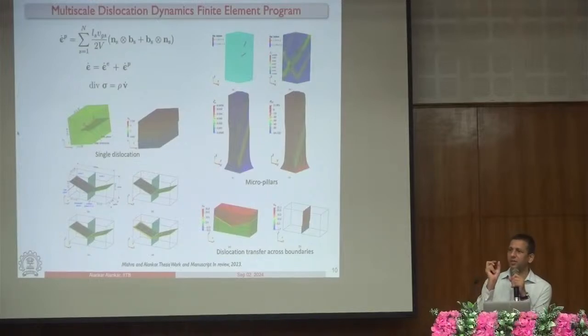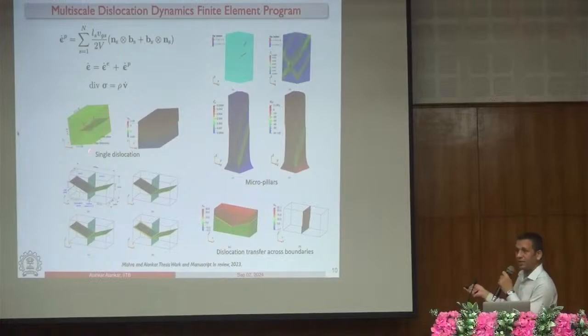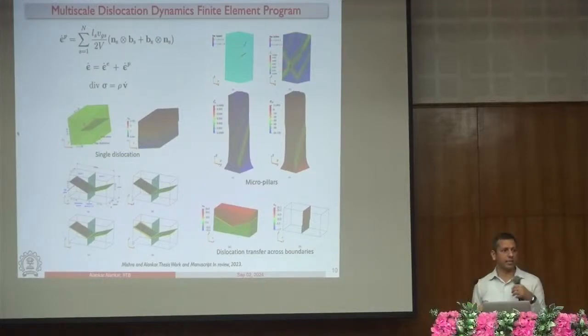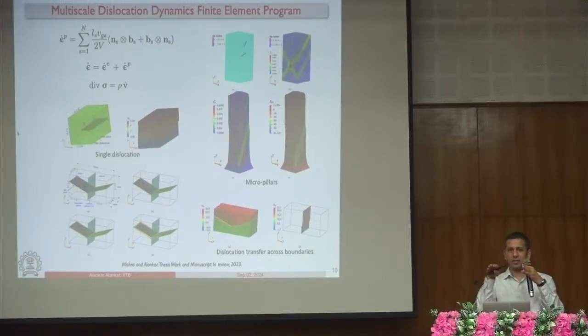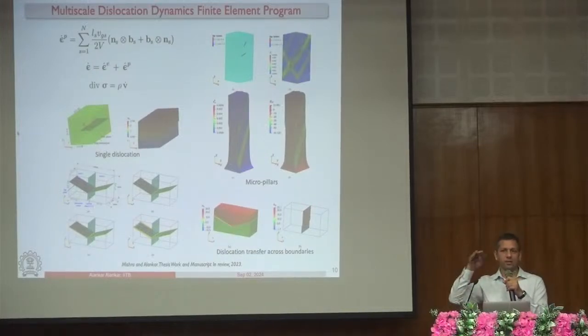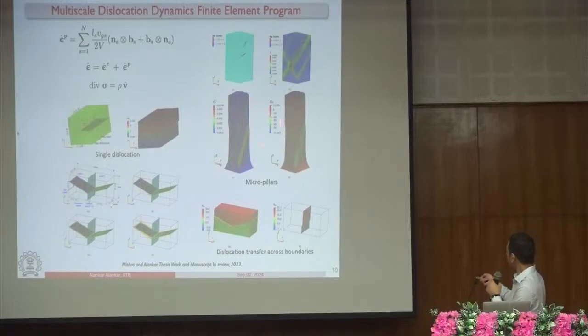Now it is my choice whether I introduce a single dislocation in the pillar or multiple dislocations or multiple pool of dislocations. We can also study things like what is the stress field of dislocations, how the dislocations, if they are on one side of the grain boundary, if you apply a shear stress, whether they interact with the grain boundary and how they pass, what is the stress at the interface and so on, right? In this example, you see there are two dislocations in the beginning and you compress it, the dislocations will start bowing. They'll become more dislocations because they multiply as you deform. And some of the dislocations will escape the surface. And when the dislocations escape the surface, they leave a step. And that's the step that you saw in the first slide. There were multiple steps, right? So these are the simulated steps that you are seeing here.